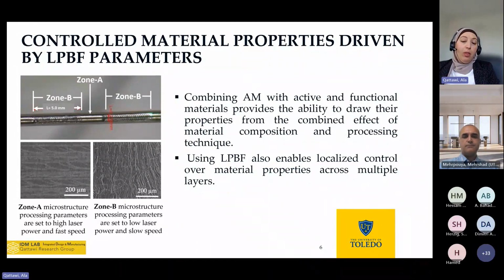So you can see, for example, here that if we change the processing parameters on a laser powder bed fusion machine, that will yield a totally different microstructure within the same composition of the powder, same composition of the component, everything the same. The only change is the processing parameter, basically how much energy we're pulsing on the powder in order to melt it and create the part. So eventually we will have different mechanical properties if we control these process parameters.